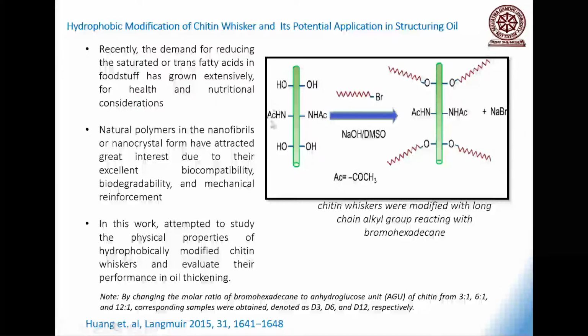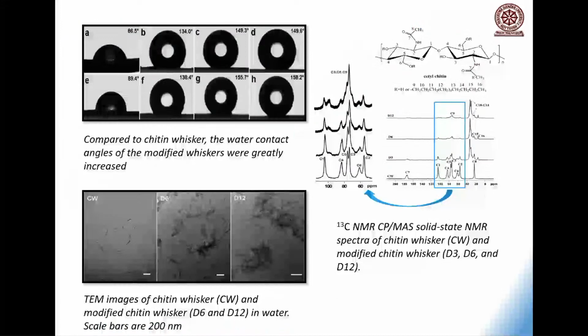In this structure, if you do a small chemistry, reacting nanochitin with bromohexadecane, the idea is to introduce alkyl groups on the surface of nanochitin. You can control the chemistry very easily. You can control the length of the alkyl group. And if you do that, you can make super hydrophobic surfaces.